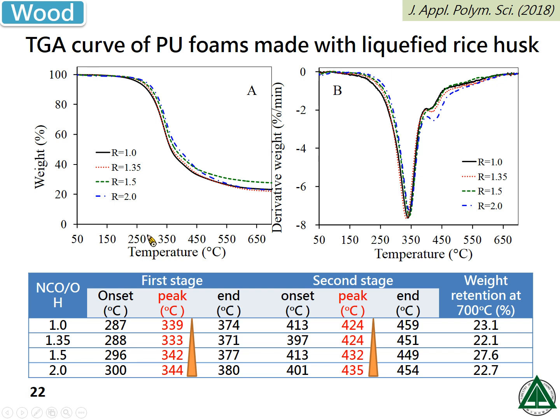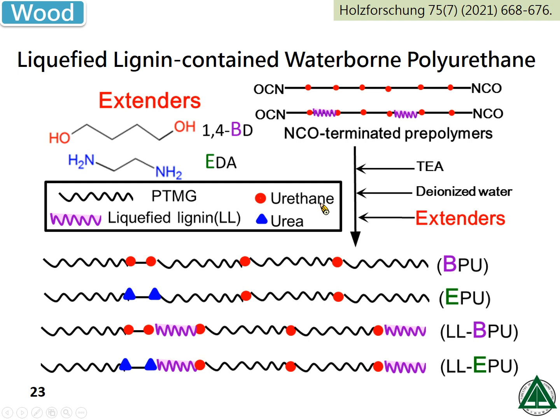We use the TGA curve to check the thermal property. As you can see, increasing the NCO ratio and using liquefied rice husk can increase the thermal property. So maybe next time we can use some silica materials or just use liquefied rice husk. Then we can increase the thermal property. Organic solvent is dangerous and toxic. We can use liquefied lignin to synthesize waterborne polyurethane. So the solvent is water, which is really safe.